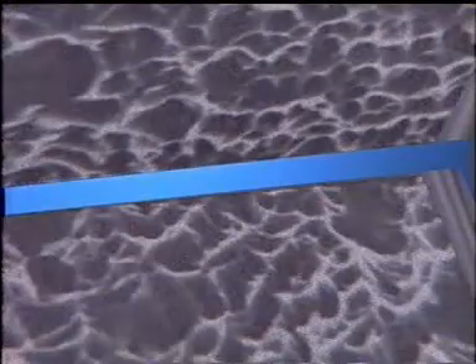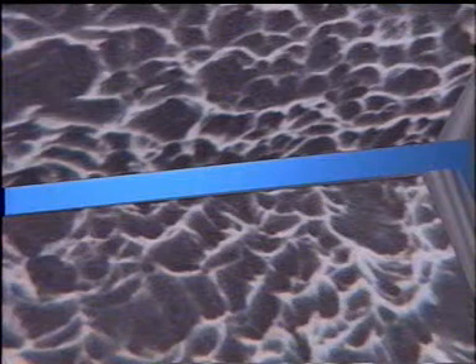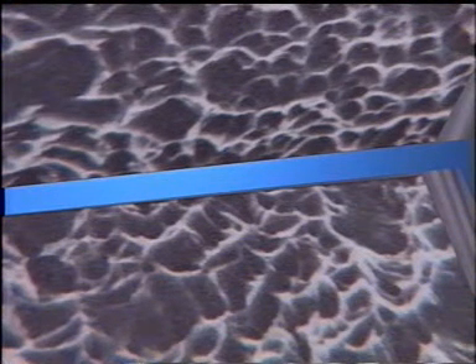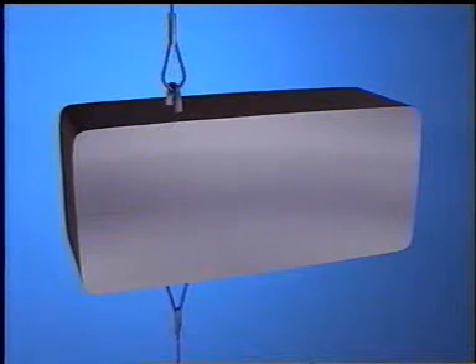The shape of the dimples is governed by the state of stress within the material as the microvoids form and coalesce. Under conditions of uniaxial tensile load, which applies a generally uniform strain across the section of metal, the resulting fracture essentially forms equiaxed or round dimples. Depending on the microstructure and the ductility of the material, the dimples can exhibit a very deep conical shape, or they can be quite shallow. The shape of the dimples can vary with the mode of stress applied to the metal.